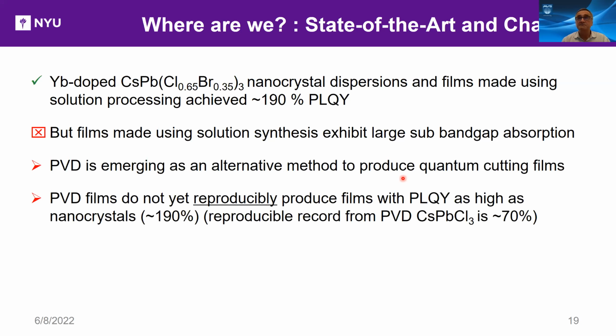So we've been working on this. PVD films do not yet reproducibly produce films with photoluminescence quantum yield as high as nanocrystals, 190%. But we don't think that's a fundamental limitation, because there are PVD reports of close to 190%, but they're not as robust as one would wish. We in our lab, and we know from others, consistently get things approaching 70% with cesium lead chloride. This is Ivor's work that we're about to submit.